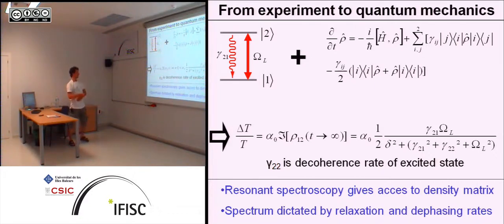And for a two-level system, we can now do some maths, and then we basically end up with this representation. Because we don't do pulse experiments, but always continuous wave experiments, we always look at the steady-state solution of the system. And therefore, this absorption contrast I've shown you of the resonant laser is, for a two-level system, given by this standard Lorentzian equation, where you have the relaxation. Here, gamma 22 is the dephasing rate, and also